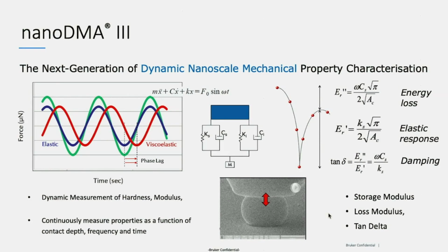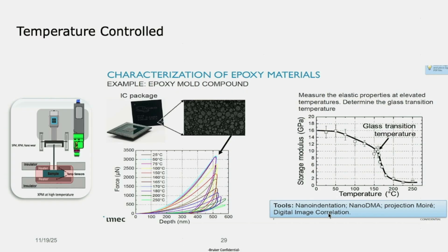Okay, so this allows us to measure the E prime, E double prime. It's very useful for evaluating viscoelastic materials like polymers or biomaterials. We also provide a very accurate temperature control stage. It allows you to measure the modulus across different temperatures, so you can see the modulus change. This makes it easier for us to understand the polymer glass transition temperature, which we call Tg.